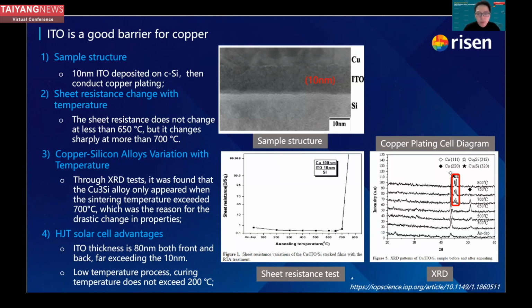And even if there's some breakage of the silver shell of the low silver content pastes, for our heterojunction modules we are adopting 80 nanometer ITO. So this is a very good barrier for the copper element. So this also verifies that we don't have such a risk.